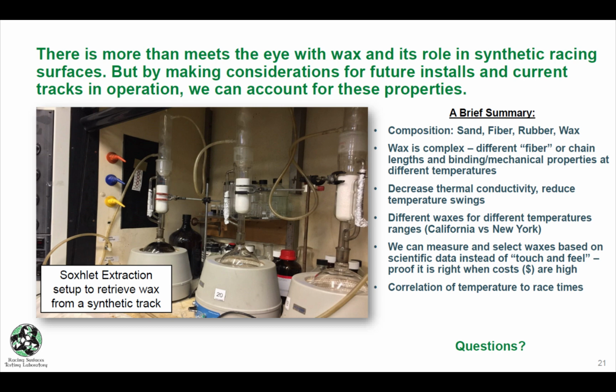So there's definitely more than meets the eye when it comes to synthetic racetracks. We have a whole array of testing that we can do. The wax is complex. You're going to have different fibers, different chain lengths, and they're all going to affect how the material binds and what kind of mechanical properties we're going to have at different temperatures. We know that if we can decrease the thermal conductivity and make it more resistant to changes in temperature, you can reduce these temperature swings. We know that we can select waxes based on different temperature ranges, and we can measure and select these waxes based on data instead of the touch and feel approach, and provide the evidence and proof that this is the right material when the costs are so high. And of course, we know that there's a correlation to race times.